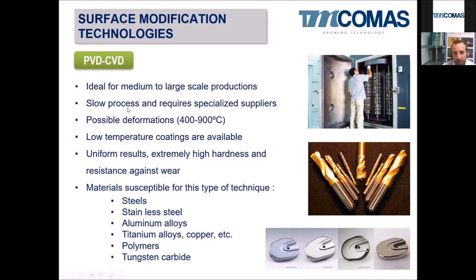It's a slow process and requires specialized suppliers because it is a vacuum process, so it has to be people that know how to use the vacuum technologies, and well, it has to be specialized suppliers. Possible deformations, because some of these coatings are done or created between 400 and 900 degrees C, so it has to be kept in mind that depending on the shape and on the deformability of the parts, it can be some bad experience. There are also some low temperature coatings available in recent years, especially diamond-like coatings at 180 degrees, 200 degrees, which gives you extremely high hardness and extremely resistant coatings, but very thin, 3 to 5 microns.